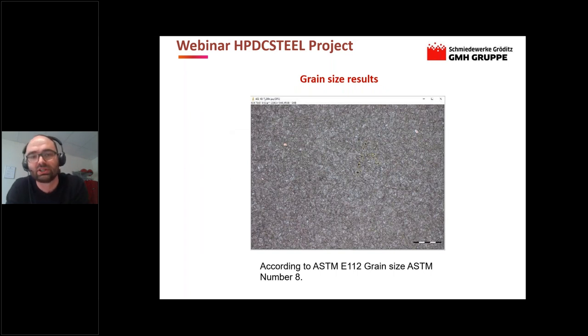In this picture, we can see the grain size, which was determined according to ASTM E112 in hardened and tempered condition. As a result of the forging process with a high forging ratio, the grain size was determined according to ASTM number 8. A typical requirement is that predominantly ASTM number 7 is required. We have achieved this requirement, and our final result is even a little bit above it.